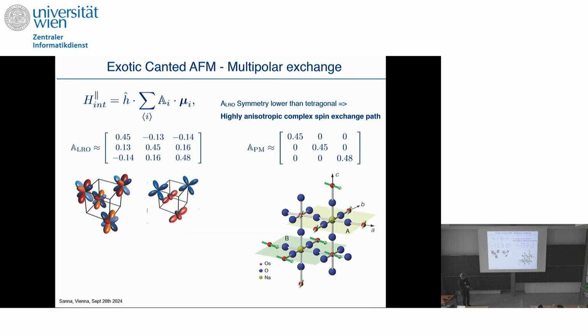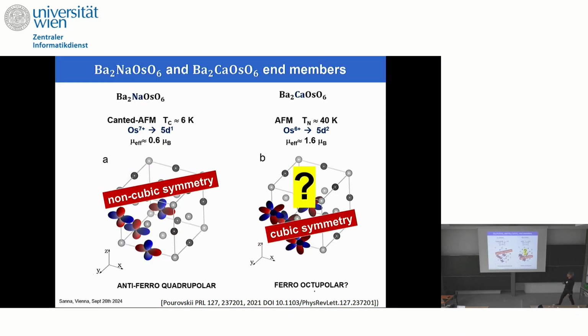And this is possible thanks to the fact that in the NMR measurements, the sodium is coupled by hyperfine coupling to the osmium magnetic moment. And by NMR, it is possible to study the form of the hyperfine tensor. If you have an isotropic, symmetric situation, or almost isotropic, you typically have a zero of the off-diagonal terms, while in a more complex anisotropic spin exchange path, you expect to have something like that. And this can be measured by NMR.